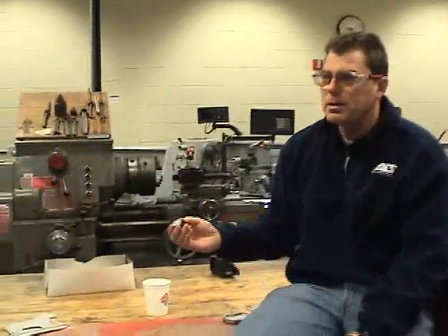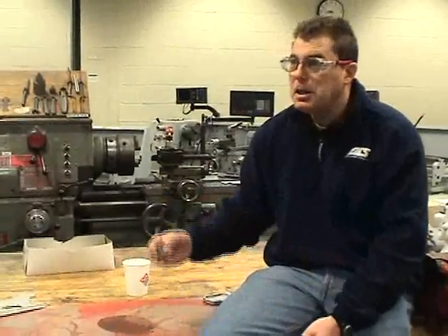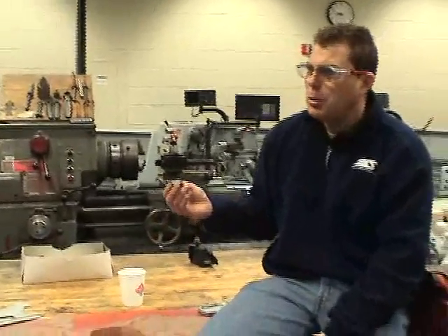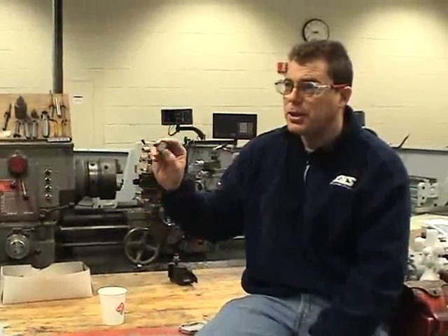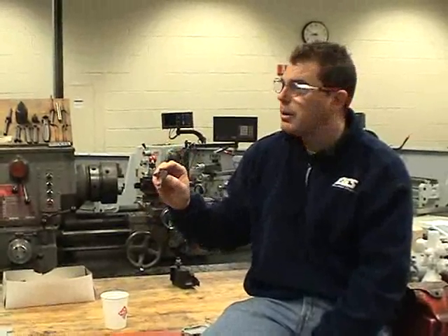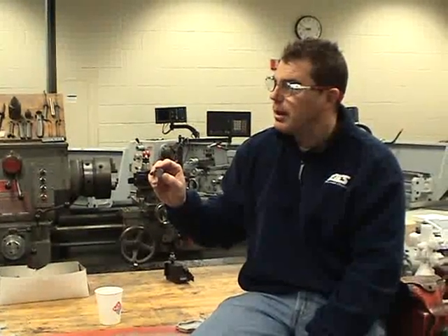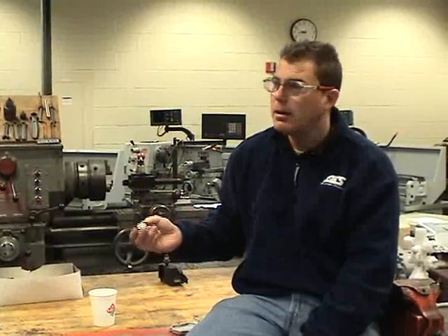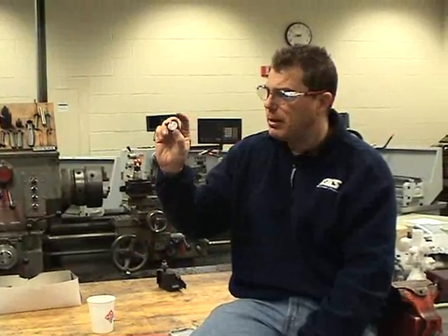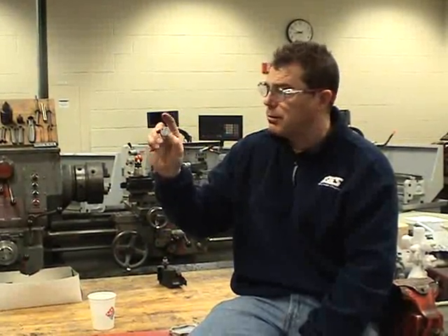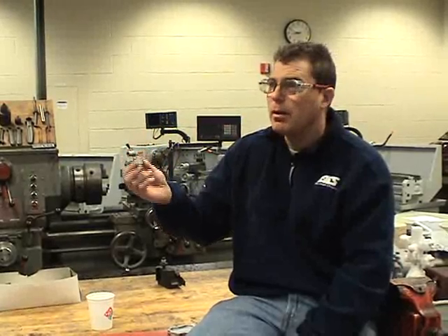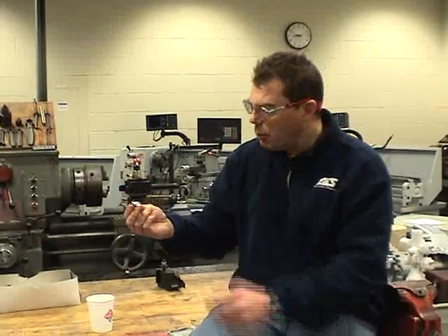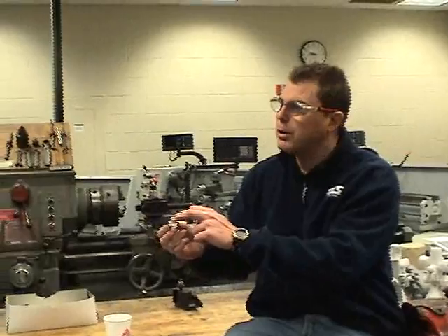Once in a while, if you get a really nice oxidized surface and you sand it, it'll look like it's kind of shiny. But if it's not shiny silver, if it's shiny gray, you've just polished the iron oxide. You need to break through the iron oxide, especially when we do the annealing where it's been in the furnace for 10 hours or something like that. You want to actually sand into that base material a little bit.